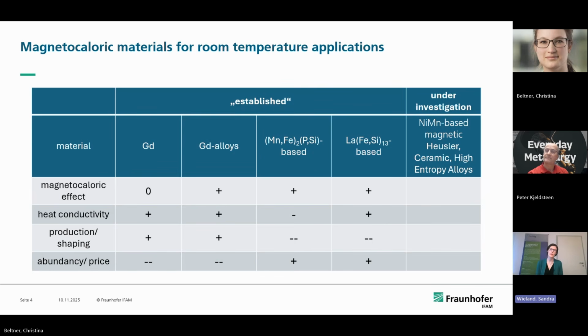That was first done with the gadolinium alloys, but there was always the problem that gadolinium, as a rare earth, is really expensive and rare. And it was always not really a good thing for broad application. Then people came up with 2 other classes of alloys, and these are the manganese, iron, phosphor, silicon alloys, and lanthanum, iron, silicon alloys. And there are some more elements thrown into this. Those 2 alloys also have this first order magnetocaloric effect, so a very high effect at a special temperature. But to really use them, to really build a fridge with it, you also have to do this cascading of the composition.